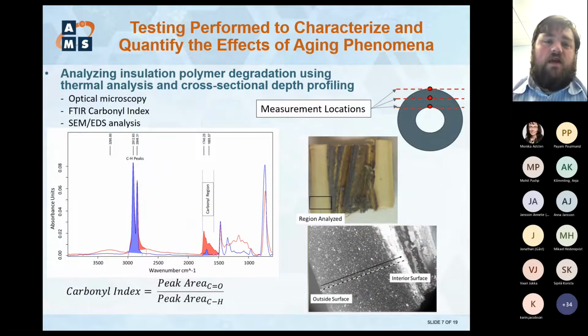So to characterize and quantify the aging phenomena, I mentioned things like diffusion limited oxidation and copper catalytic effects. We've employed, very similarly to the previous presentation shown a little bit ago, profiling techniques, basically cross-sectional analysis techniques, actually looking at different depth profiles of the materials, from the outside surface to the middle to the interior where the insulation is in contact with the conductor, if it's aged in that configuration.